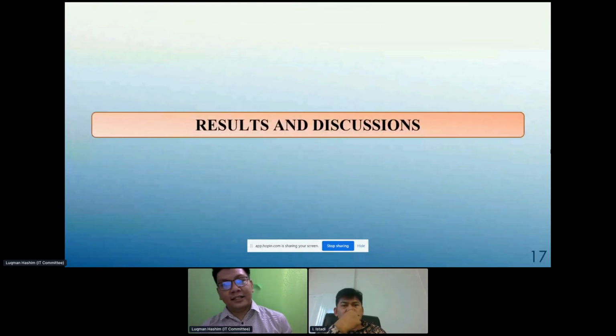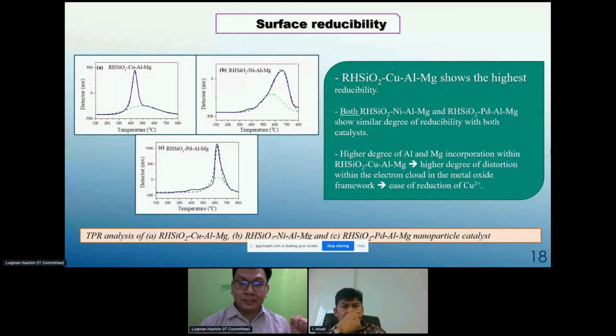Okay, we are finally entering the results and discussions. For surface reducibility, we obtained this via TPR, temperature programmed reduction. I'm just going to draw you to the main points of the results and the analysis. Copper has the highest reducibility compared to nickel and palladium, the copper system, I mean. Its reduction temperature is at 400 compared to the others at 600. And we attributed this to the much higher incorporation of aluminum and magnesium into the structure itself, leading to the distortion of the electron cloud around the copper 2+ and easing the reduction. This will help in increasing the effectiveness of the hydrogenation portion of the reaction.